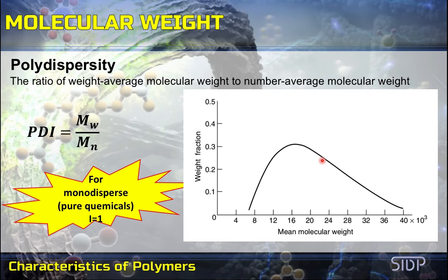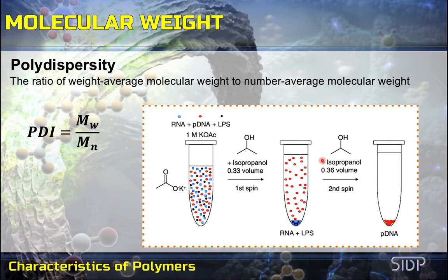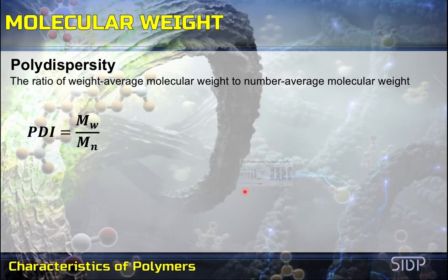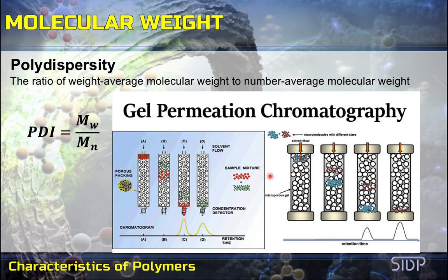Information regarding molecular weight distribution is necessary for a proper choice of polymer for optimum performance. A variety of fractionation techniques, such as fractional precipitation, precipitation chromatography, and gel permeation chromatography, or GPC, based on properties such as solubility and permeability, which vary with molecular weight, may be used for separating polymers of narrow size ranges.